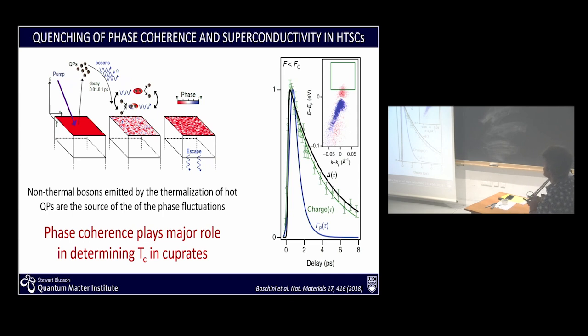And so I'd like to first start off with a cartoon. What is actually happening here? You have a condensate, you come in, you're pumping the system, you're creating hot quasi-particles. Those hot quasi-particles really are removed from the condensate, but that doesn't reduce the phase coherence of the condensate. You're just removing quasi-particles. However, they have to thermalize. And as they thermalize, they do so by emitting, creating a population of non-thermal bosons. And these non-thermal bosons are the ones which are responsible for fluctuations of the phase of the condensate, and so the loss of condensate.